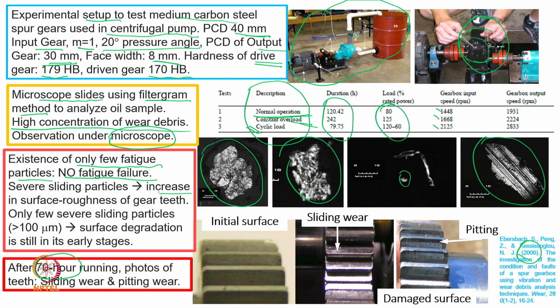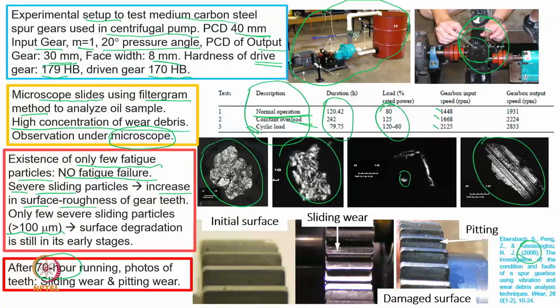Another thing, they found a number of particles which indicates severe sliding wear, and however, they found only a few particles which are more than 100 microns. When only a few particles are more than 100 microns, that means the surface degradation is still in the earlier or initial stages. If we take away these causes, we can really minimize the surface degradation. However, they did all this under the overload condition and high speed condition, and what they finally found is shown in the initial surface photograph that has been shared.